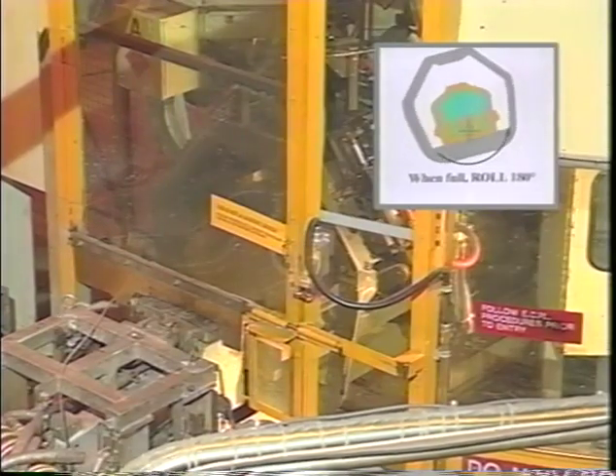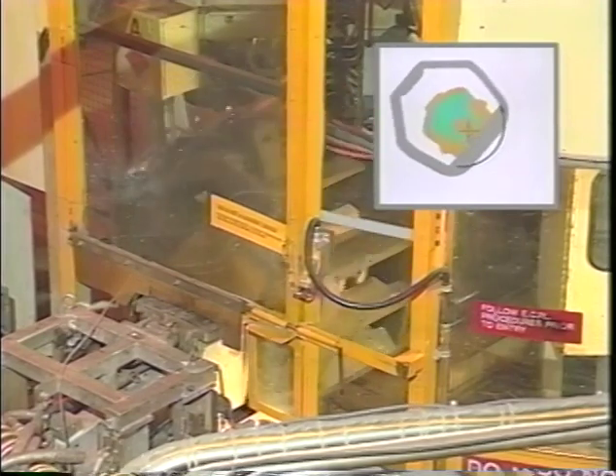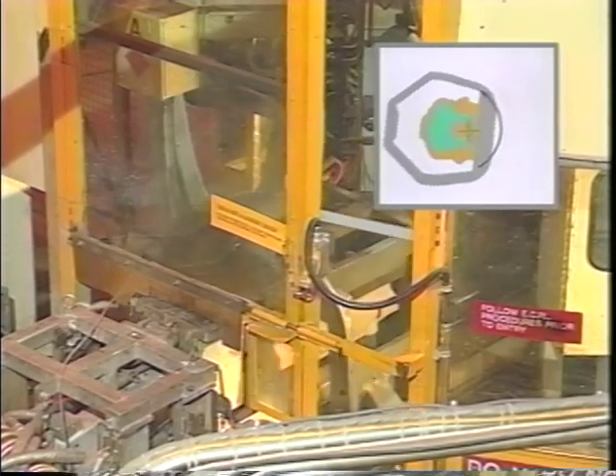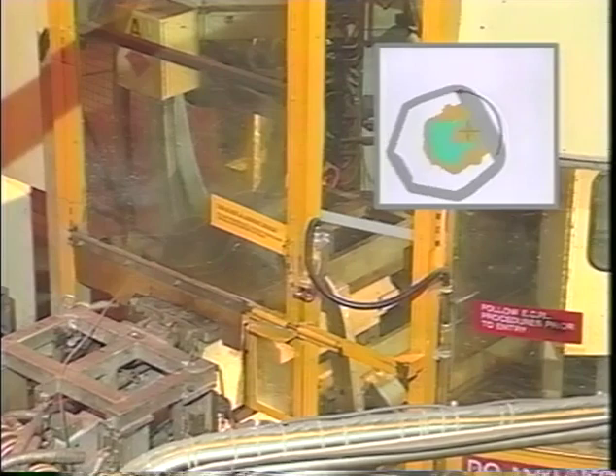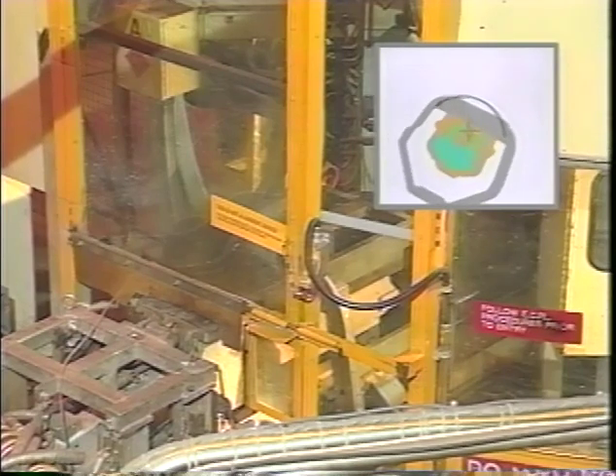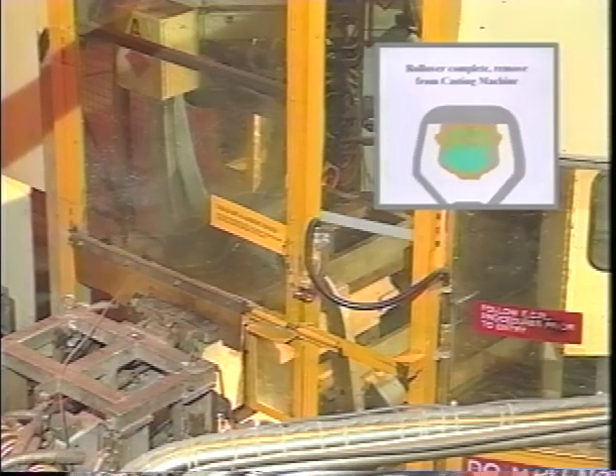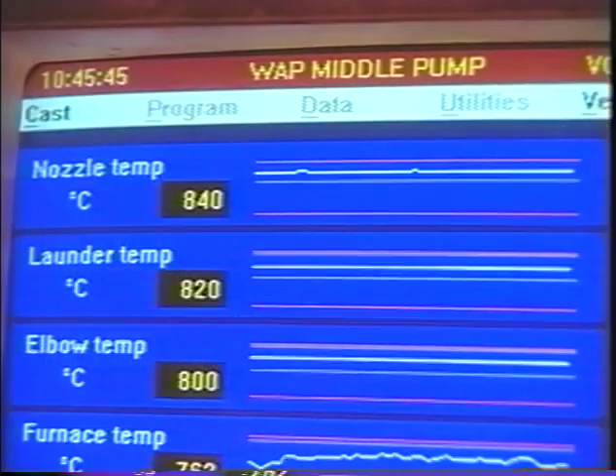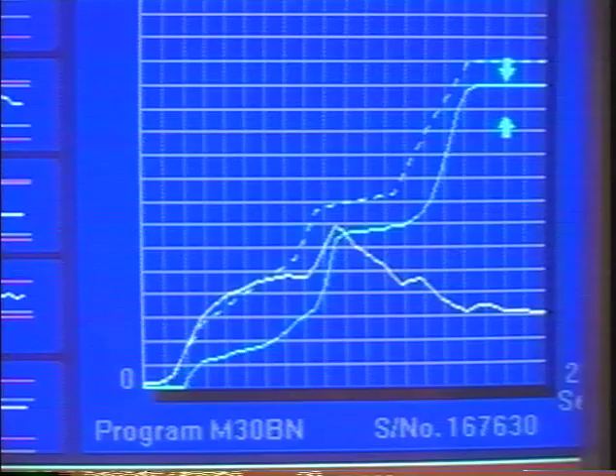Because the hottest aluminum is then at the bottom, the mold is automatically rotated 180 degrees. This prevents convection currents from forming, resulting in a significantly higher quality casting. Rollover was a Cosworth theory that was never tested. It was at the original Windsor R&D Center that it was tested, researched, and applied to a production setting. A computer system integrated into the rollover station provides feedback on each mold fill.